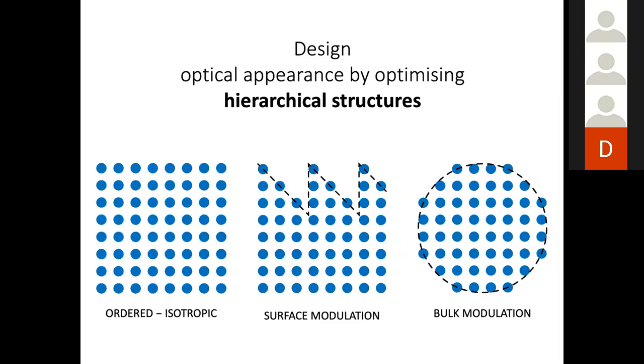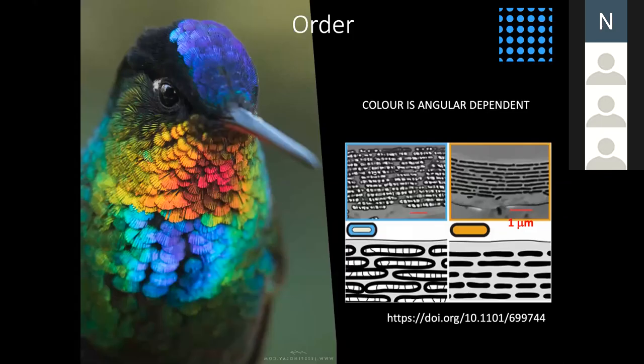Not only nature plays with how to organize these scattering elements, but also plays with what you call hierarchical architecture. So the elements are structured periodically, for example, on the scale of a few hundred nanometers, but then they are built up in even more complex structure on the scale of a few tens of microns, because generally they are organized inside living cells. So you can understand that, again, playing with this hierarchical structure, you can really change even more the optical appearance. Let me give you some examples.